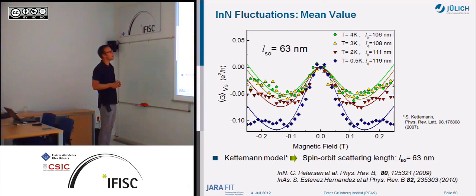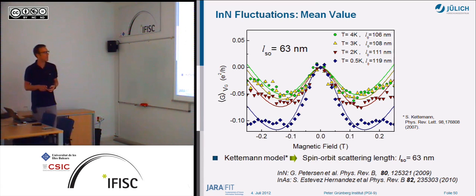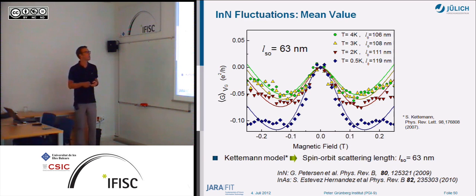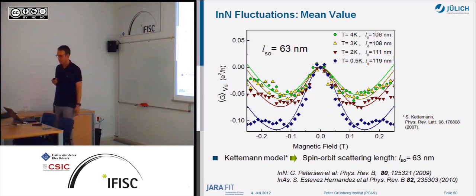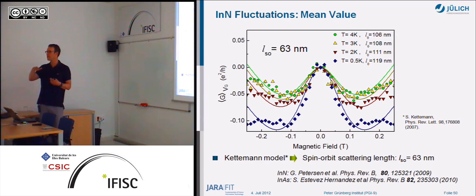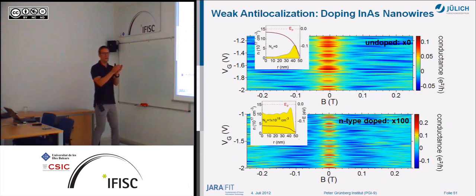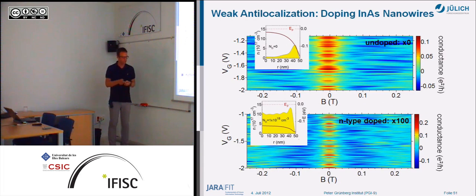This was for indium nitride, where you have this weak anti-localization peak here, and from looking at some models for one-dimensional structures, for instance from Schäpers, you can get information about the spin-orbit coupling lengths in indium nitride. It's about 63 or 60 nanometers, so quite short, quite strong spin-orbit coupling. The reason in that material why that's so strong is because we have such a strong potential, so we have a very sharp quantum well here.